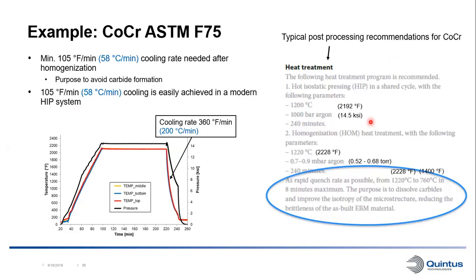And then after the HIP step, they recommend a homogenization step at a very similar temperature in vacuum, also with a 4-hour soak time. And then they have a requirement on the cooling rate. This required cooling rate corresponds to 105 Fahrenheit per minute. And the purpose of this is to avoid carbide formation in the material during the cooling. So 105 Fahrenheit per minute is easily achievable in a modern HIP system. So it would make very much sense to combine these two steps together to do one cycle in one equipment and spend 4 hours at temperature instead of 8 hours at temperature.